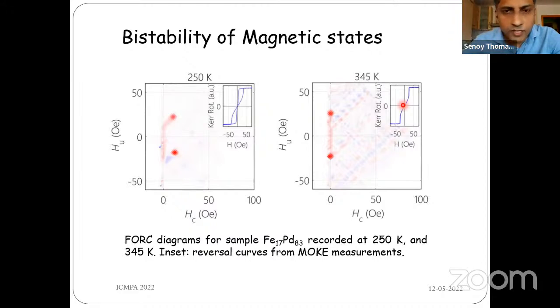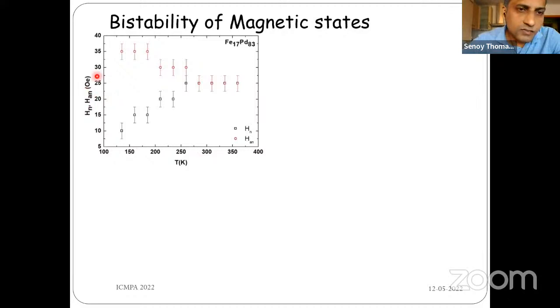So in order to understand the temperature dependent reversal process better, we recorded the nucleation as well as the annihilation field as a function of temperature. And what we found is that above a particular critical temperature, the nucleation and annihilation fields nearly overlap, which means that above this critical temperature, thermal energy will be sufficient to switch the configuration from the single domain state to the vortex state, or one could have the possibility of observing bistability of the magnetic states. And this critical temperature we label as the bistable temperature, above which we could observe the bistability between the magnetic vortex state as well as the single domain state.